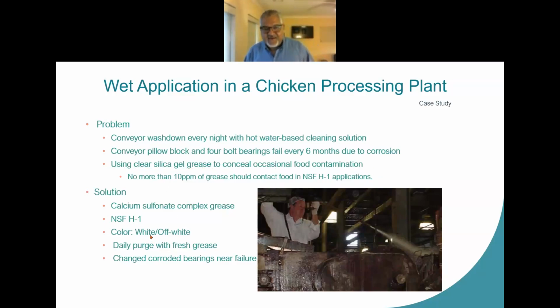Well, here's a solution I had for them. Let's use a calcium sulfonate complex grease. It's not clear, but you use greasing rates where you don't spill over grease onto your product. It's an NSF H1 grease. The color can be white or off-white. Because of the washing process, it's still a good idea to daily purge with a fresh grease, just like you're doing with your clear silica gel grease. But your bearings will last longer with our grease.